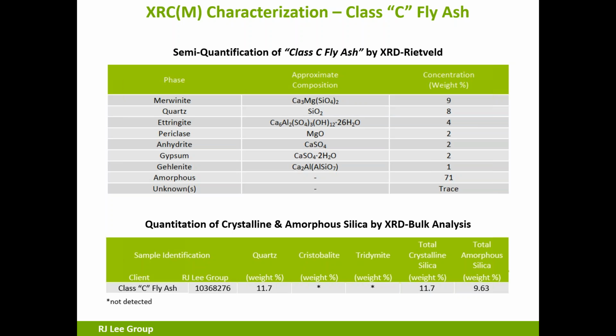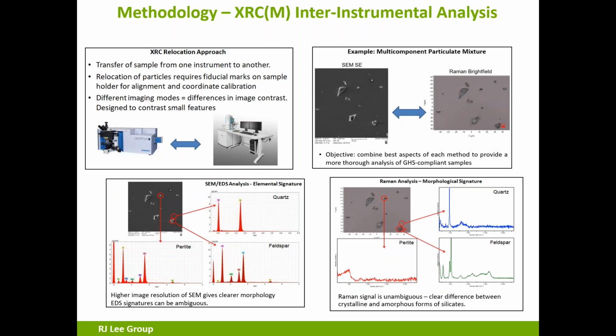Just as a comparison, quantitation of crystalline and amorphous silica by XRD bulk analysis is a process of subtraction. This same material shows 11.7% when just analyzed for crystalline silica, with 9% of the crystalline silica amorphous. So it's just a tidbit point. It doesn't really matter. It's all above the 0.1. So with this, we need to get into the respirable fraction and see how much actually respirable crystalline silica there is. To do that, and I've deleted a couple of slides, one of which explains the CCSEM process, another explains the Raman process, for brevity, but the bottom line here is we have an interinstrumental analysis approach that we can use where we lay these particles out, we spread them out proportionally across a filter, we coat it, we put it into the SEM, and we now look at the particles and determine what the concentration levels are.